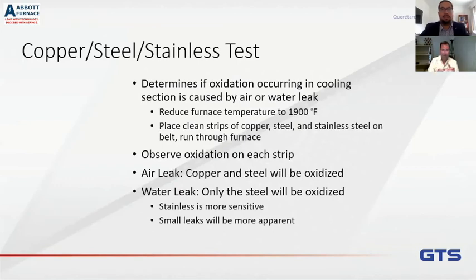Just pure copper. Then you want a piece of steel, just a plain piece of regular carbon steel, and then a piece of stainless steel or inox. And so what you want to do is take some sandpaper and clean the surface of those and get them very bright and clean. Then you're going to remove the hydrogen, and then you're going to run this through. And what's going to happen is when the copper comes out and the steel comes out, you're going to look at it. The steel should be discolored and it should match, for example, in our example, if we were looking at peacock, it should be peacock colored.